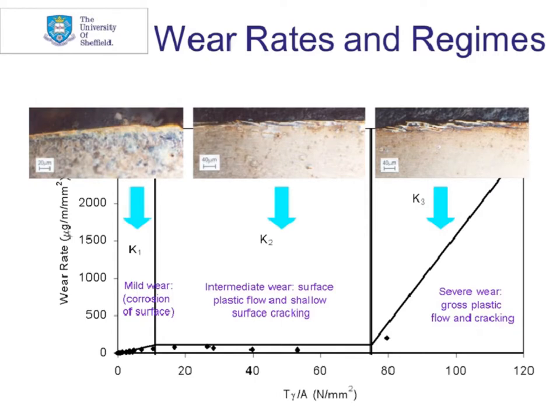Obviously, my main role within this work was to define those rates of material loss for the different contact conditions. We used an approach that's well established within the railway industry now, the T-gamma approach, relating wear to the amount of energy within the contact. So I did a lot of work looking at the different regimes of wear, from the very mild conditions you may get in the rail head wheel tread contact right through to the very severe wear you may get in very sharp curves in the flange gauge corner contact.